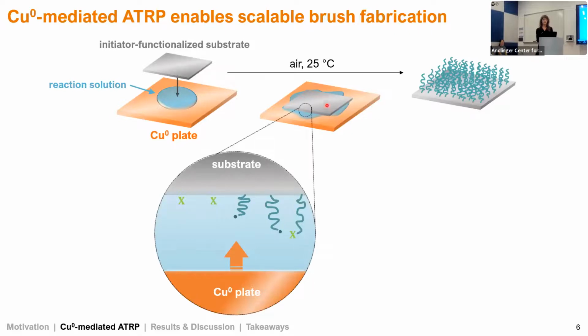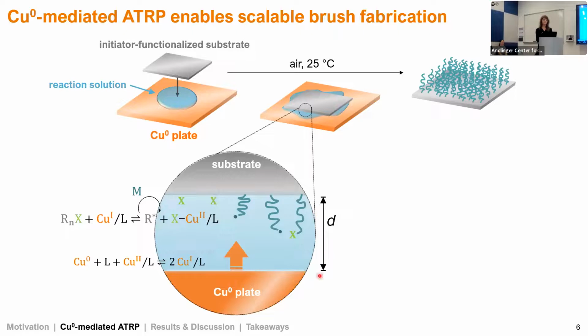So if we imagine zooming in on our reaction here, polymerization occurs in this thin film of solution between the copper plate and the substrate. So when the copper plate contacts the reaction solution, it consumes dissolved oxygen present, and copper also dissolves, and that forms our activator and our deactivator species according to this disproportionation equilibrium. So as these species diffuse to our substrate surface and they reach initiator sites, they will react according to that conventional SI-ATRP equilibrium, and we get our polymer brushes. This parameter D, which is the distance between the copper plate and the substrate, also enables additional control over our brush growth. So this was introduced in 2015 by Zhang et al.